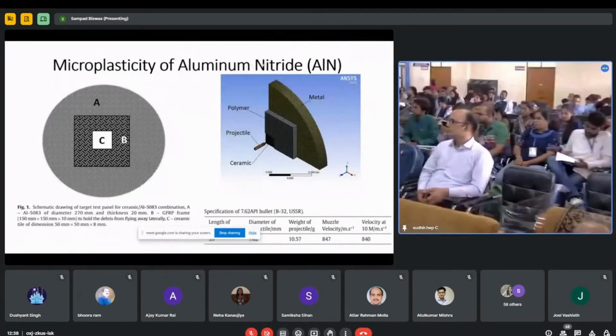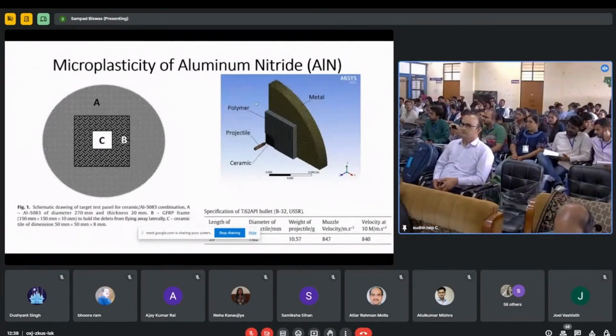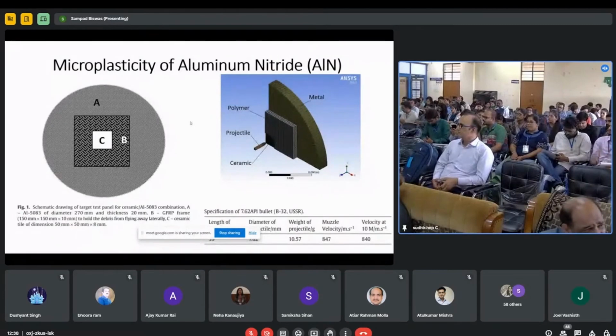So we carried out an experiment with two different ceramics. One is aluminum oxide, the other is aluminum nitride, and we wanted to see how this varies with the type of ceramics, I mean with the chemical composition of the ceramics. So one is AlN, the other one is Al2O3. Those two have two different crystal structures. One has a rhombohedral crystal structure, the other has a hexagonal crystal structure.